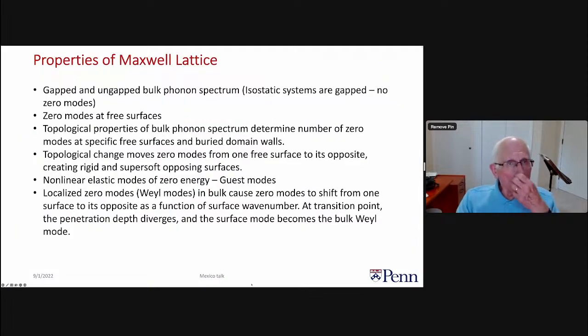So what are the properties of these Maxwell lattices? Review them before we go to the details. They have a phonon spectrum that has gapped bulk phonons. They have zero modes at the free surfaces, unlike the Rayleigh waves that you normally get. The topological properties of the bulk phonon spectrum determine the number of zero modes. In other words, these are distortions that occur at zero energy, at specific free surfaces and buried domain walls. The topological change moves zero modes from one free surface to the opposite one, creating rigid and super soft opposing surfaces. There are nonlinear elastic modes of zero energy, and you can see that in a way here.